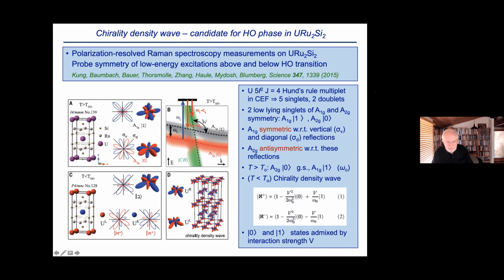And basically what the evidence, what the experiments and the theoretical interpretation give you is that you can form out of these two wave functions some new wave functions that are believed to be associated with the hidden order phase that have opposite chirality. And so as you go along the c-axis, you double the length of the unit cell, because this layer has, say, left-hand chirality, this one right-hand chirality, this left-hand, and so on, to generate this kind of a picture. And so this, they believe, is a candidate for this hidden order state.